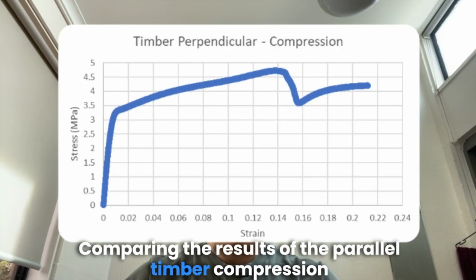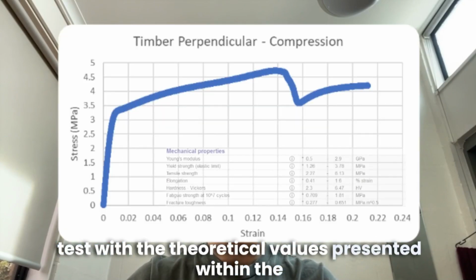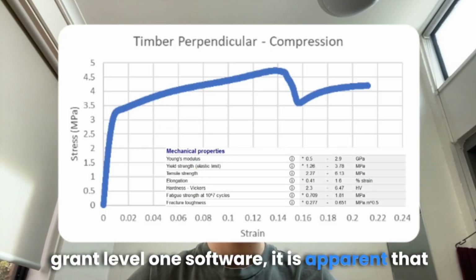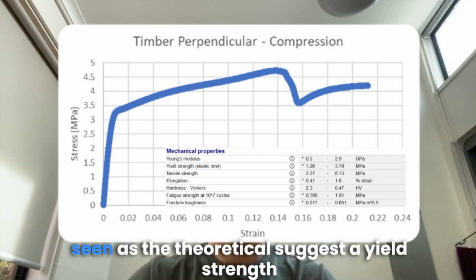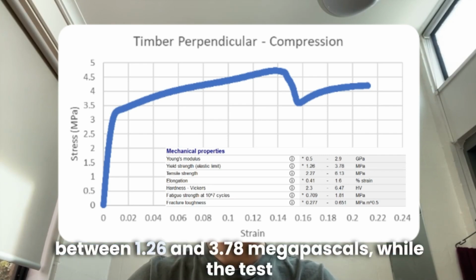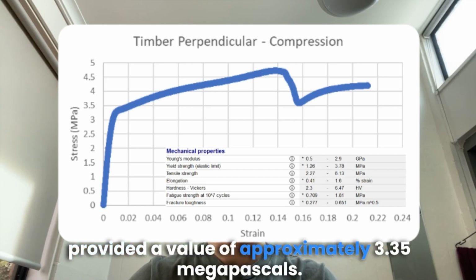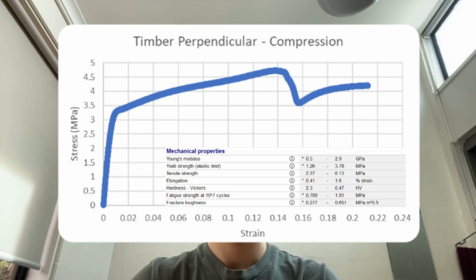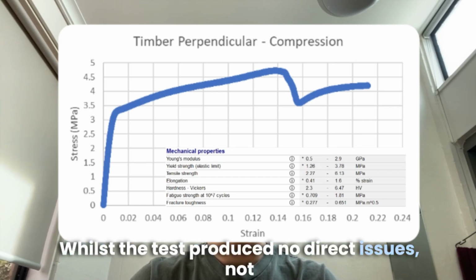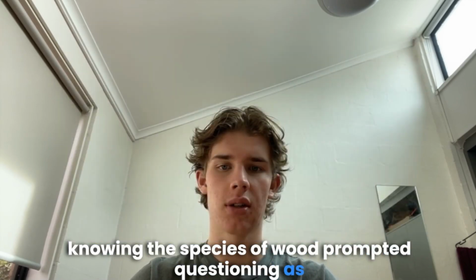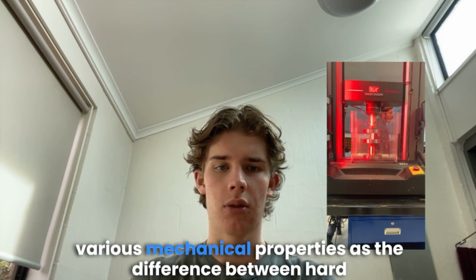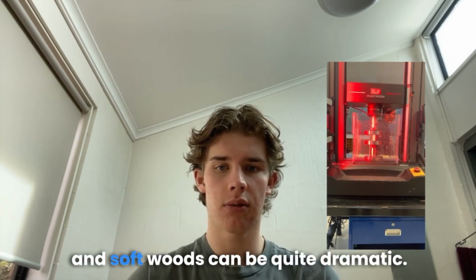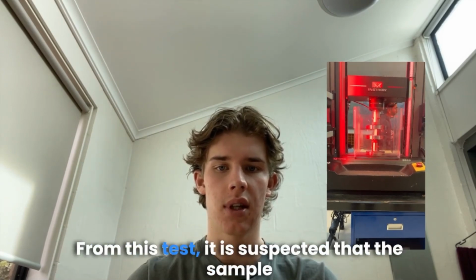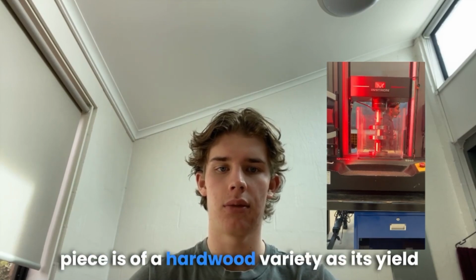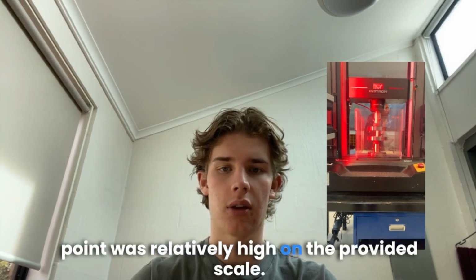Comparing the results of the parallel timber compression test with the theoretical values presented within the Granta Level 1 software, it is apparent that the result is relatable to what should be seen, as the theoretical suggests a yield strength between 1.26 and 3.78 megapascals, while the test provided a value of approximately 3.35 megapascals. Whilst the test produced no direct issues, not knowing the species of wood prompted questioning as to what values should be obtained for the various mechanical properties, as the difference between hard and soft woods can be quite dramatic. From this test, it is suspected that the sample piece is of a hardwood variety, as its yield point was relatively high on the provided scale.